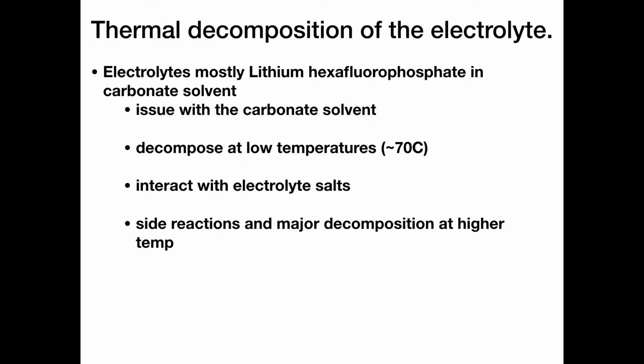The higher the rate, as everything increases, again, this just kind of becomes thermal runaway. And reactions occur that increase heat, increase pressure. More reactions occur, more things are made. And instead of actually getting electrons due to oxidation and reduction, we just get fire. And we get an explosion. And that's not what we want. So heat in general, if it never makes it to the anode part, it could just be the decomposition of the electrolyte itself, causing some issues.